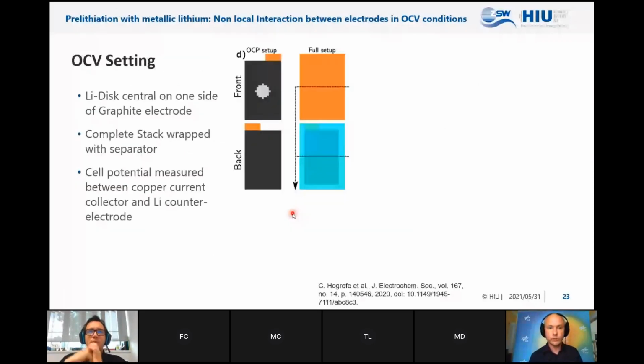So what we did is we used this lithium disk, put it on graphite. This is how it looks from the back. Then we also used the separator, and we put a counter-electrode lithium on the other side. So there were interesting results on how the lithium is dissolving. I mean, why is it dissolving? It is because you have directly two conductors on top of each other with different Fermi levels. And these different Fermi levels mean that you get an electronic current from the lithium to the graphite. So you dissolve via this process lithium in the electrolyte.